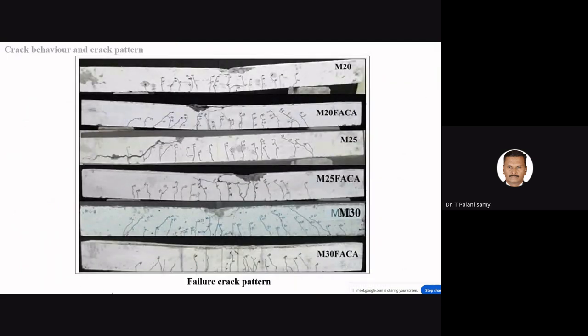Now the failure crack pattern. It is an interesting crack pattern observed here. Here you can see M20 concrete. They have fewer cracks compared to the M30 faca, right? You can see this now, no? M30 faca. We can see the number of cracks is more, it's correct. We measured, no? What is the load here? You see. Okay. So the number of cracks is also more in case of M30.